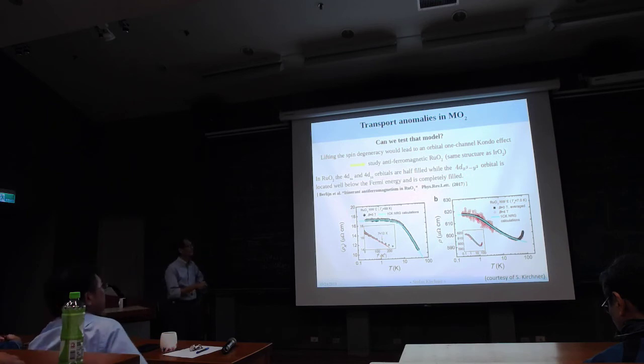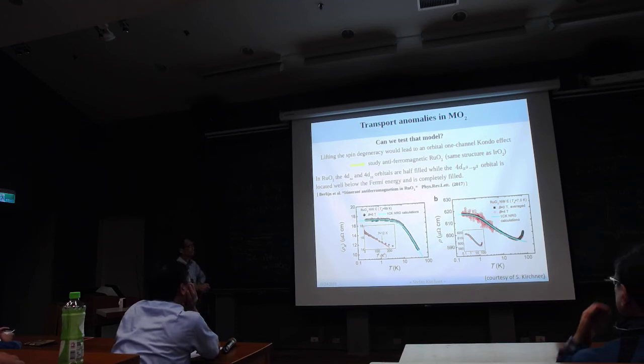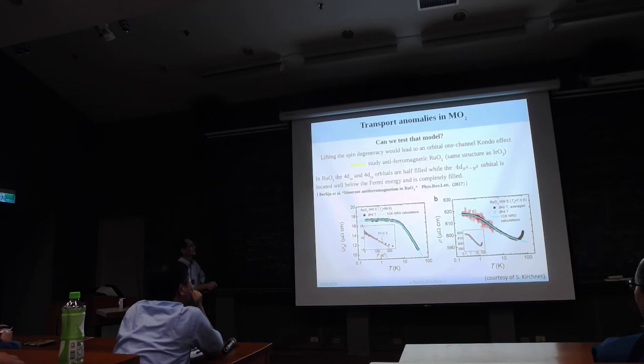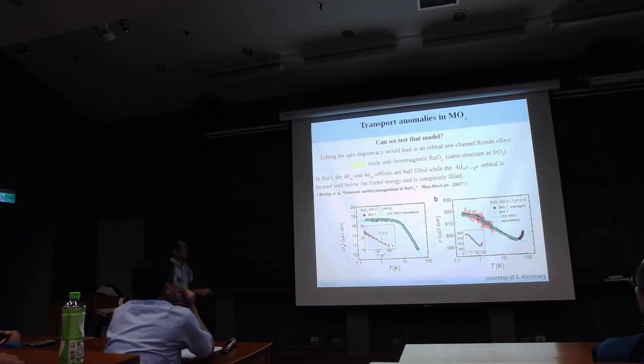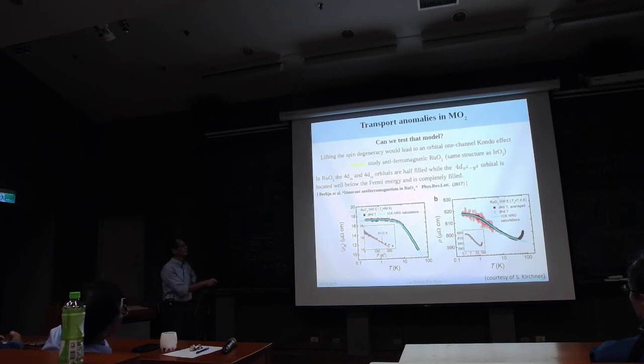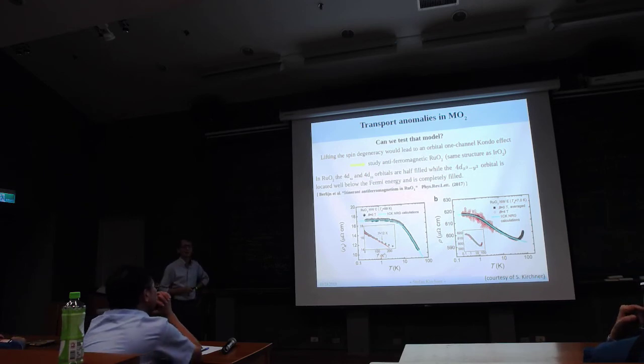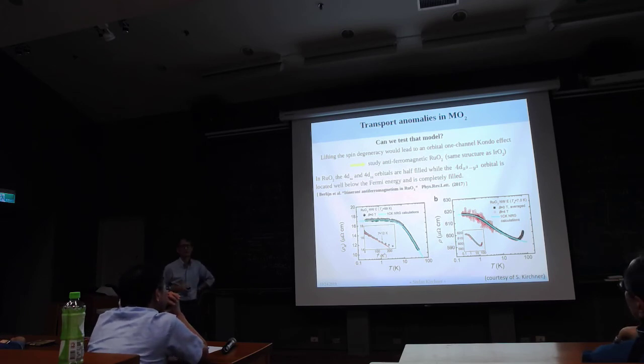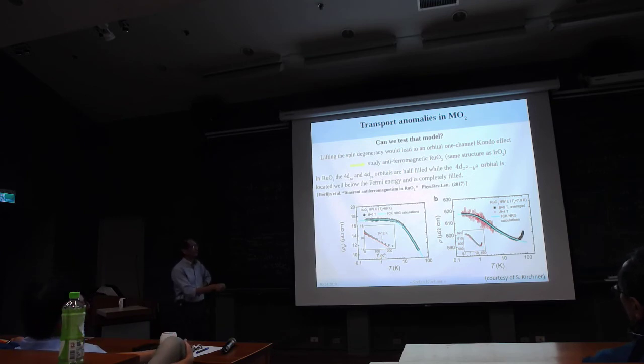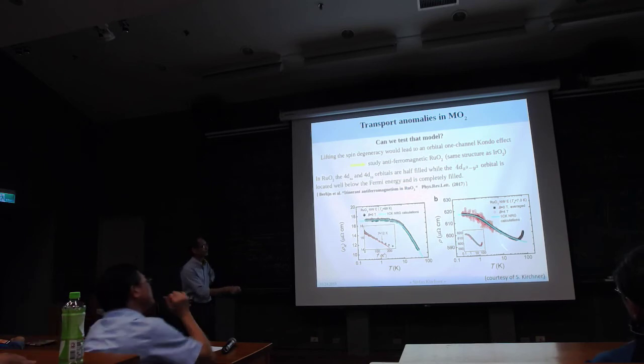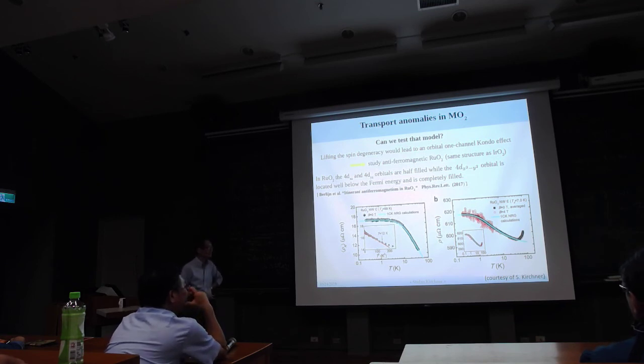So here are the ruthenium dioxide nanowires. In zero field, the resistivity shows logarithmic temperature dependence. And if you go to very low temperatures, it goes back to T-square dependence. That's what I told you. If you have only a one channel Kondo effect, when you go to very low temperature, you should recover Fermi liquid behavior, so there should be a T-square dependence. This is what we see. In this case, for example, this light blue curve is the 1CK scaling from the numerical renormalization group calculations. It actually collapses closely on this curve.